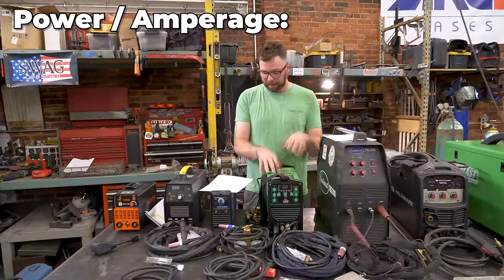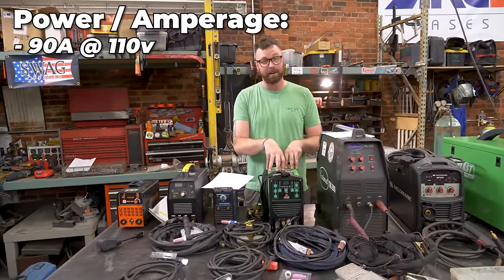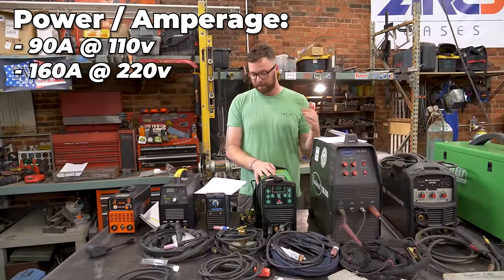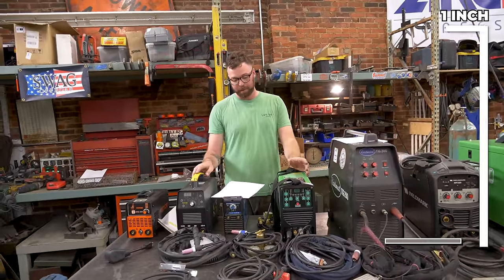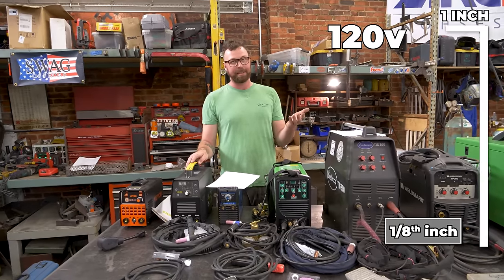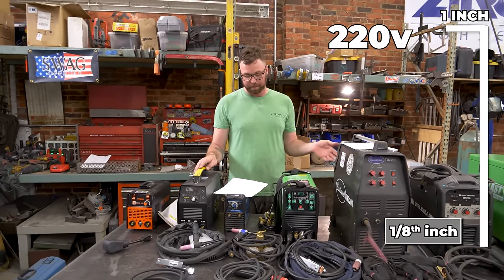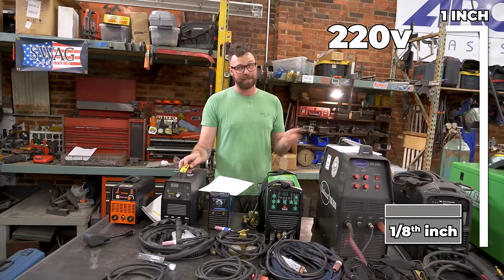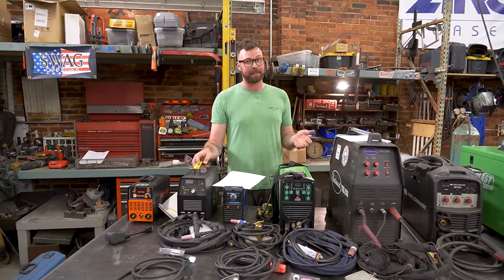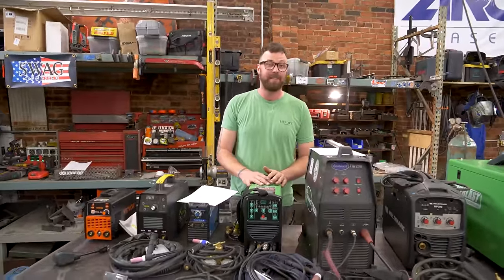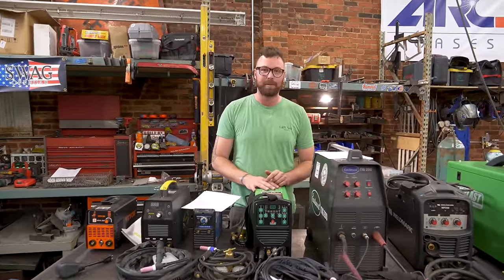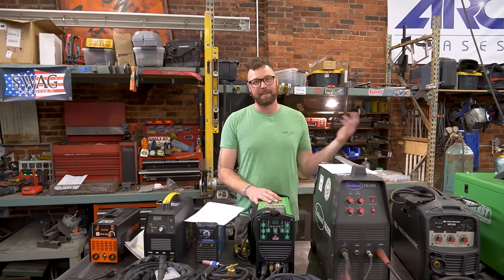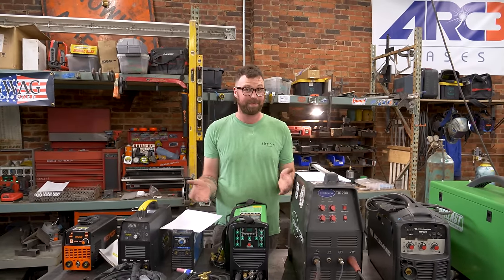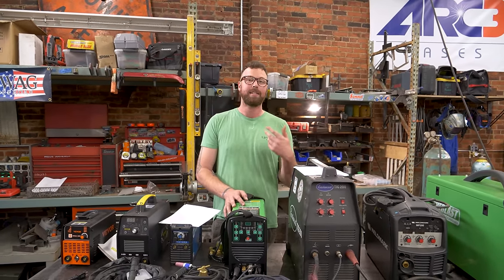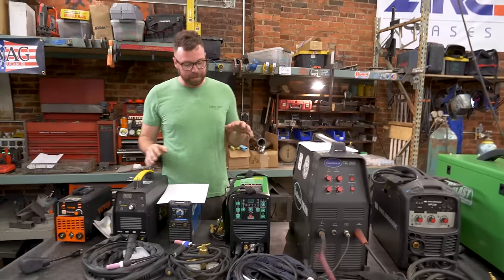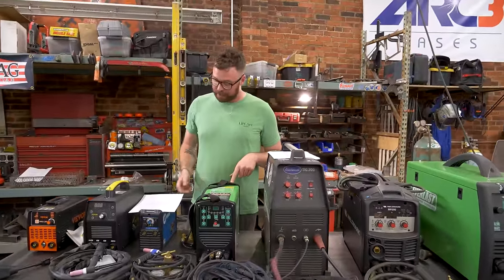So power and whatnot, this runs at 80 amps on 110 volts, or 90 amps, sorry, which is pretty impressive. And then 160 amp peak on 220 volts. At 120 volts, it'll go down to 28 gauge steel and weld up to 1/8 inch steel on a single pass. At 220 volts, it'll do the same minimum and a 3/16 maximum single pass DC TIG steel. That's pretty big. That does 90%, if not more, of the DC TIG welding I do in this shop. If I'm welding much thicker stuff, personally, I tend to bias towards a MIG welder. So this is likely the only TIG welder you'll need in your shop for steel, stainless, titanium, DC operations.